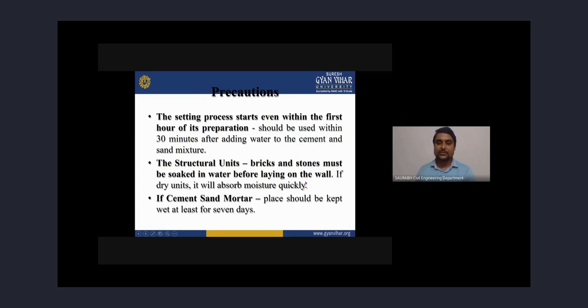The setting process starts even within the first hour of its preparation, so it should be used within 30 minutes after adding water to the cement and sand mixture. The structural units, brick and stones, must be soaked in water before laying on the wall. If a dry unit is used, it absorbs moisture quickly. Cement sand mortar should be kept wet for at least 7 days.